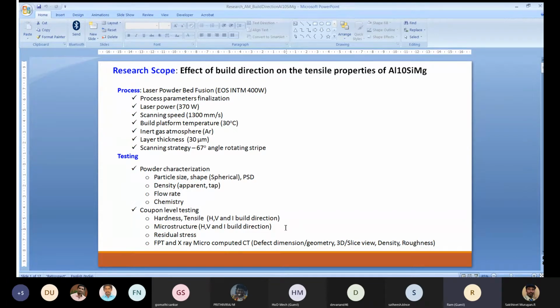Scanning strategy is very important. We have adopted the 67 degree angle rotating stripe method. What it means is, let's say I build the first layer at 0 degree. The next layer will start from 67 degree. The third layer will start from 67 into 2, that is 134 degree. Like that, each layer will be 67 degree away from the previous layer. That's called the 67 degree rotating stripe method.